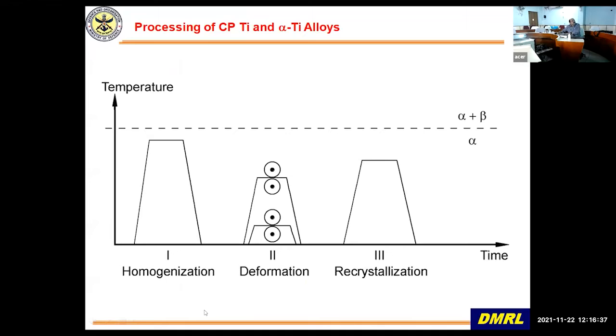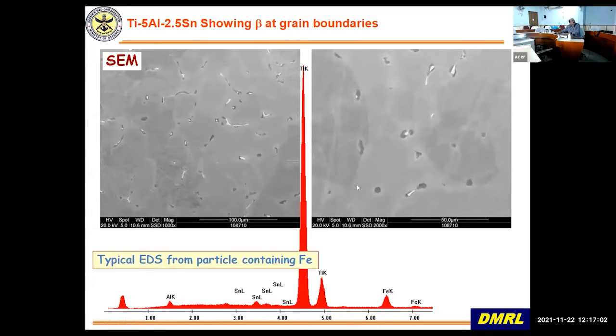I will show you how the alpha titanium alloys are processed. It is homogenized high up in the alpha regime only, and then deformed in the alpha regime, and then recrystallized again in the alpha regime, slightly higher than the deformation temperature. That is how these alpha alloys are processed. It is completely processed in the alpha regime. Here is an example of microstructure. This is of an alloy with 5 aluminum and 2.5 tin, and you can see there is a very slight amount of beta which controls the grain size, and there you have iron for stabilization of the beta phase. Otherwise, it's a single phase alloy.